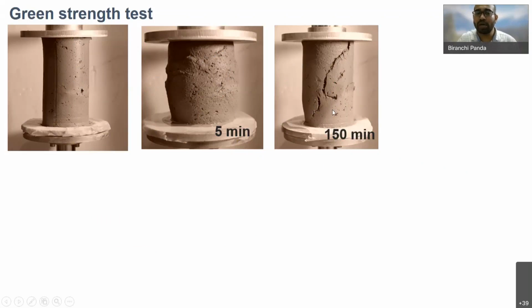This is most important in concrete printing, because you are printing a large structure, so maybe the first layer will be deposited at 5 minutes, but the last layer will be deposited at 150 minutes. So the material behavior will change, because concrete will harden with time. So it is very important to know how your material behaves at different time intervals. To get more knowledge about the green strength, we conducted this test where we compress the material at different intervals of time to know the load bearing capacity.